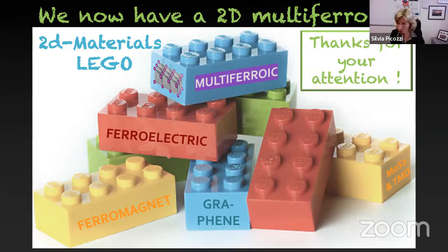We did everything for the monolayer. We didn't do it for the bulk, but actually you can, of course. So here the way it was done was really taking two spins, counting them, and calculating the contribution of these two spins. In bulk, what you can do is set up the spin helix, and also from layer to layer, usually I think you have an antiferromagnetic coupling, and then you can calculate the bulk polarization, the overall, the units. But yeah, it can be done. It can be done for sure.